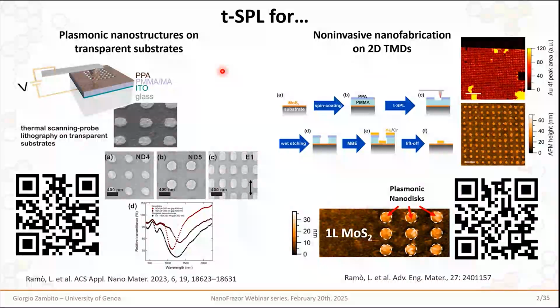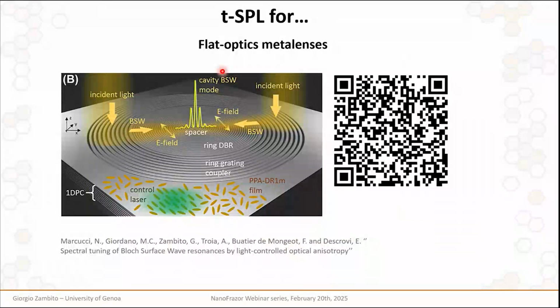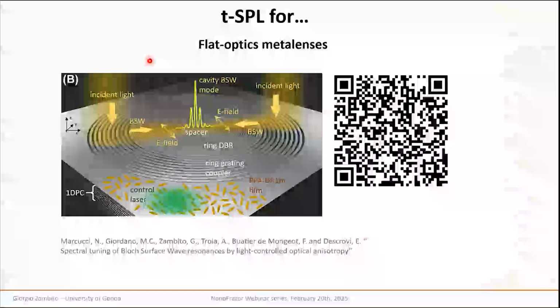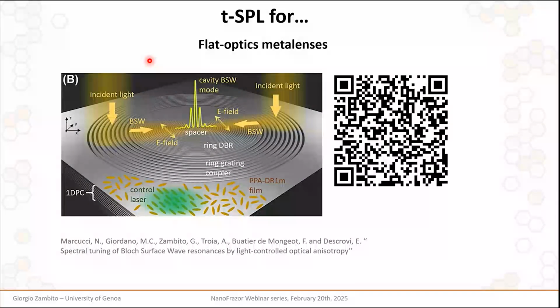Another field where the NanoFrazor can give some advantages is flat optics, with the capability to fabricate metalenses with sub-wavelength features. For example, in this work, we employed NanoFrazor lithography to achieve spectral tuning of Bloch surface waves, with controlled behavior depending on a controlling laser light. This is also a field where having the capability to embed this kind of metalenses in a condition where all other techniques such as electron beam lithography fail can be very useful.